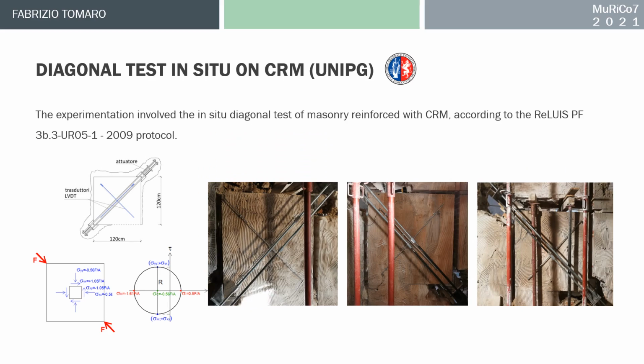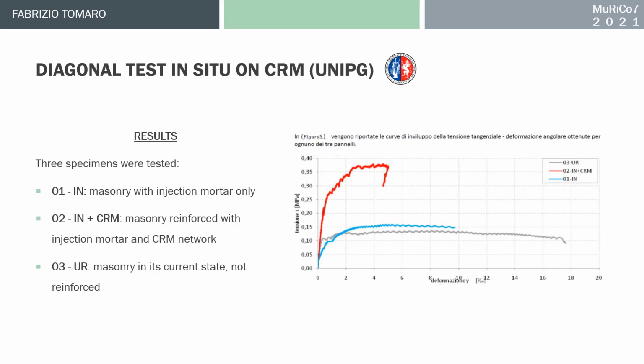For the CRM system, diagonal tests have been carried out at the University of Perugia in order to investigate the increases of resistance offered by the system on masonry panels obtained in situ. Tests were performed on 3 different panels. The first is a masonry panel with hydraulic lime mortar injection, the second is reinforced with mortar injection and CRM reinforced plaster, and the last is an unreinforced panel. The tension and strain graphs show an important increase in the masonry panel reinforced with the injection and CRM reinforced plaster compared to the other 2 panels.